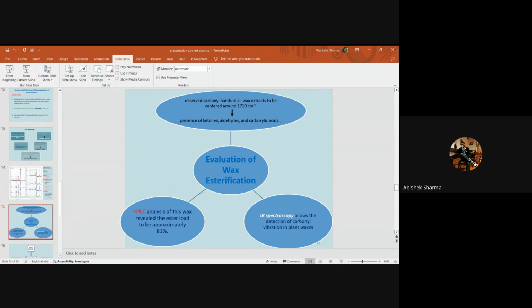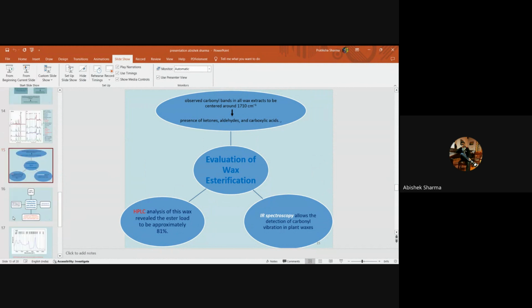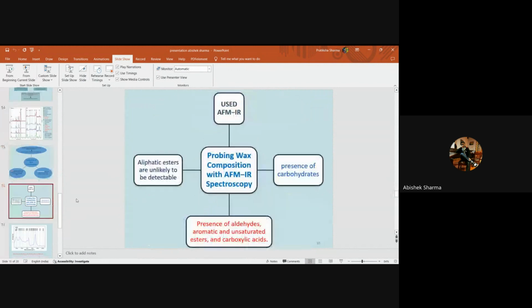We also found that IR spectroscopy allows the detection of carbonyl vibration in the plant waxes and also the structural moiety. And they also found out that the wax ester load in the wax of Sorghum bicolor was approximately 81% through the chromatography technique. Now, probing wax composition with AFM-IR spectroscopy. Here we used AFM-IR spectroscopy, that is also called atomic force microscopy infrared spectroscopy.